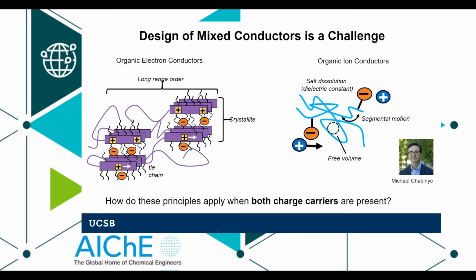And that last piece turns out to be a fundamental problem, which is what I'm going to talk a lot about. Electron conduction, whether you're talking about in polymers or in other materials, really relies on crystallinity. In polymers in particular, it relies on your chains lining up well enough that you can get pi orbital overlap and get a charge to move from one side to the other. Ion conductivity in polymers relies on your polymer being able to move out of the way so the lithium can move. These are non-compatible requirements.